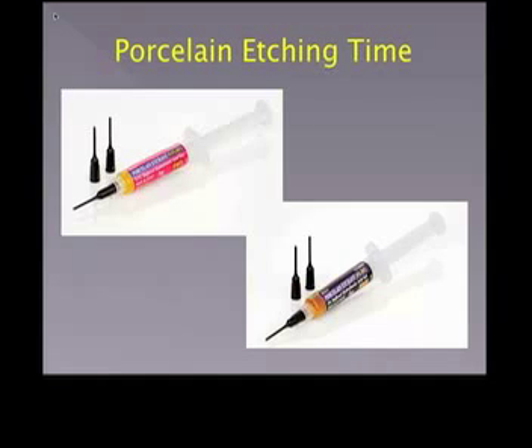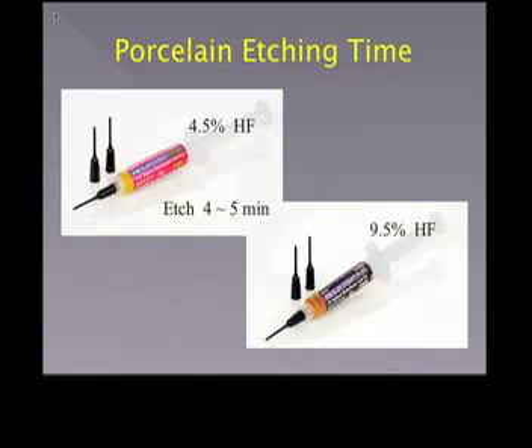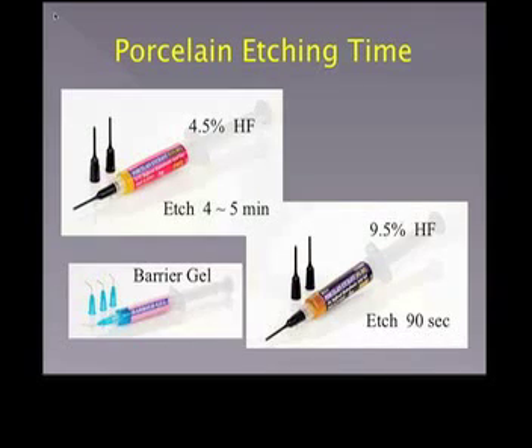Etching glass containing substrates provides a much-needed mechanical retention. And until now, it's been confusing how long we etch with hydrofluoric acid. We've actually only had a 4.5% hydrofluoric acid solution. BISCO's created a 9.5% hydrofluoric acid solution, and what this does is it decreases the etch time that you need. Typically, it's 4 to 5 minutes for the 4.5%. You only need 90 seconds now with the 9.5% solution.